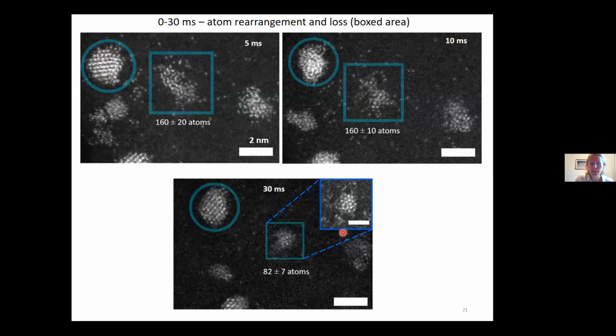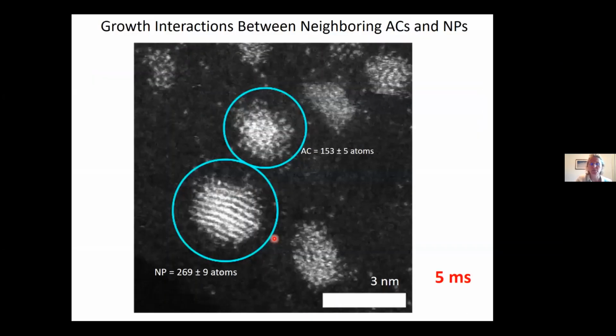And then after 30 milliseconds, in order to become stable, and this here is a crystalline nanoparticle, it has actually lost atoms. So it was interesting, because you often think of growth as always things growing inside. But for those of you who have considered processes like Ostwald ripening, things can also get smaller in size in order to reach a crystalline state. So this has gone from an amorphous cluster to a single, smaller crystalline nanoparticle.